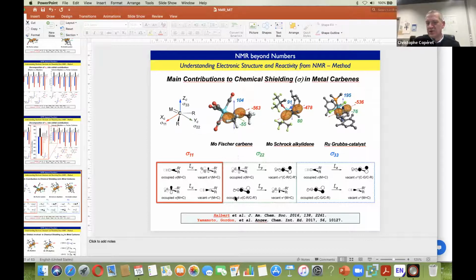When you see that, it means that you have a very different electronic structure, which is related to making something more sp2. That means the metal has a lot of electrons and gives back to the metal center. Then you start to make what we call hyperconjugation, and you see that appearing. So it is a case-by-case basis, but I would say in most instances, what we have found is 1,1 is driving, in a few cases you see that 2,2 is driving, and in a few cases 1,1 and 2,2 can invert.